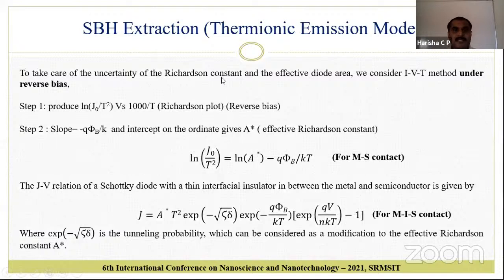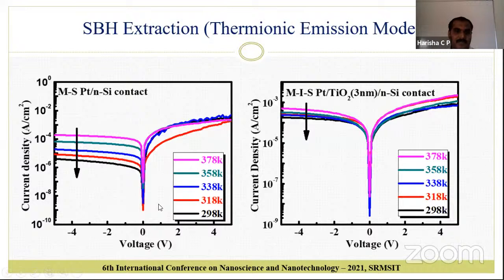By considering the uncertainty of Richardson constant and effective diode area, we have used a thermionic emission model to extract the Schottky barrier height, where the IV curves will be done at different temperature levels. In our research work, we have done IV characterization at 5 different temperatures, starting from 298 Kelvin to 378 Kelvin with the 20-degree intermediate states.